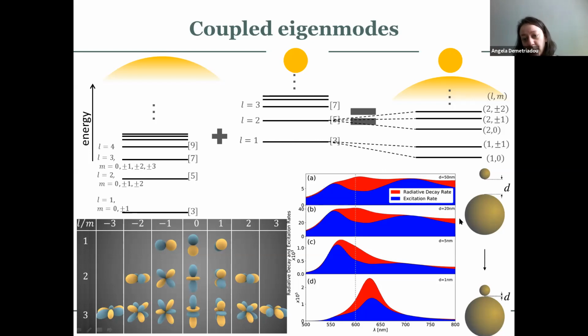So as I start bringing the small nanoparticle closer and closer to the larger one, so this is a gap of 20 nanometers and a gap of 5 nanometers, the same difference remains between the radiative and the excitation rate, but I also see that these modes here that I had before do actually reduce in intensity. What you're seeing is that you have a field enhancement much stronger within this region because of the coupling of the two systems. So I'm basically enhancing this mode, and you end up not being able to see these modes because they're weaker. So you see the scale difference on the order of magnitudes here. So this part becomes about 5 orders of magnitude stronger than this one. This still exists, it's still somewhere here, but it's so small that I cannot really see it in this system.